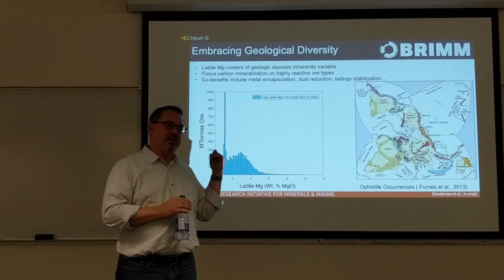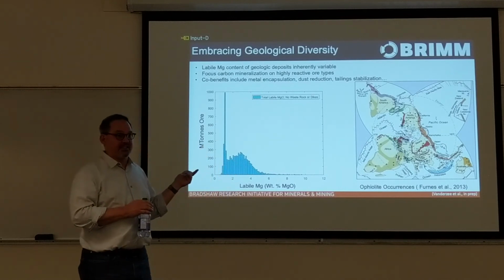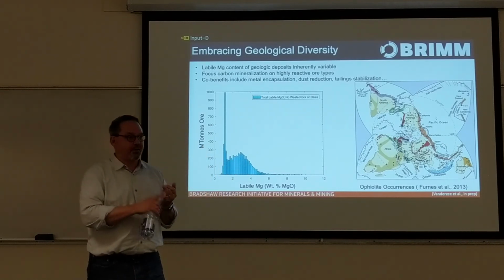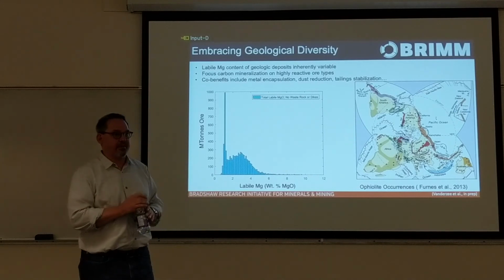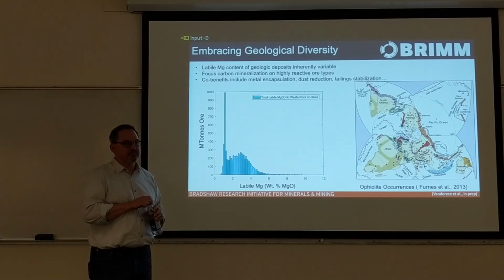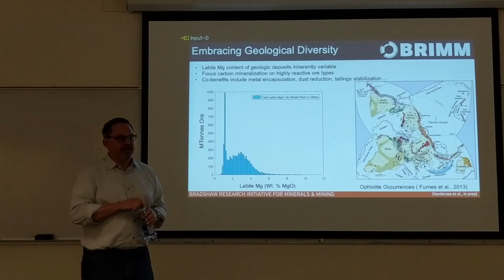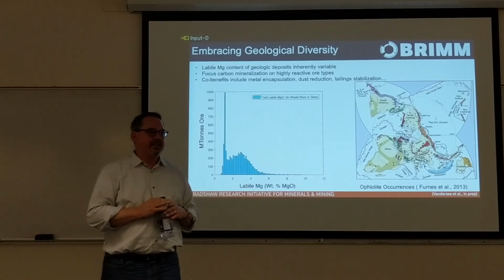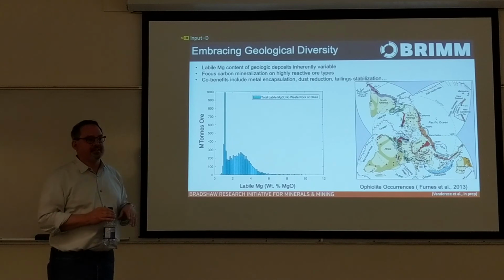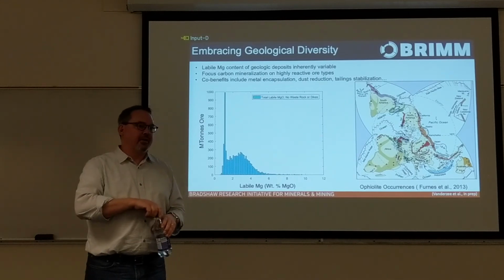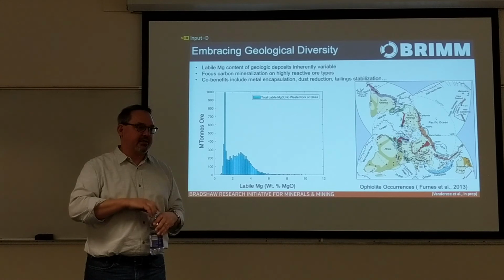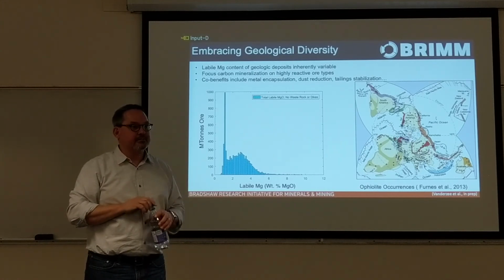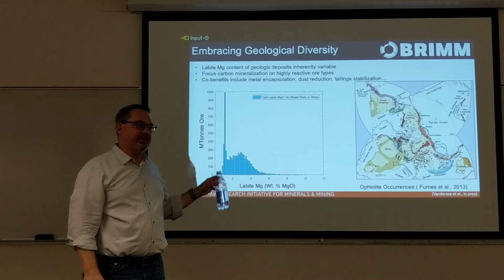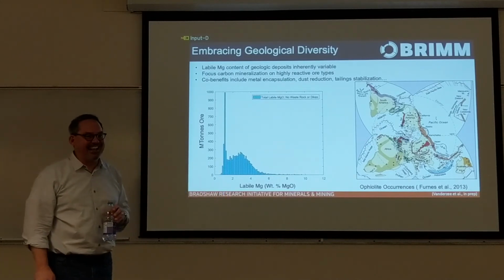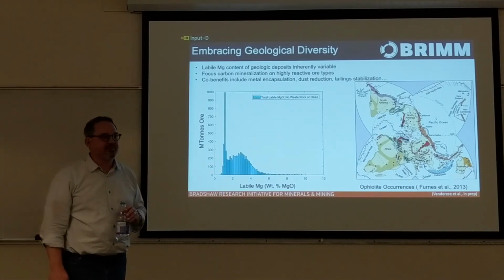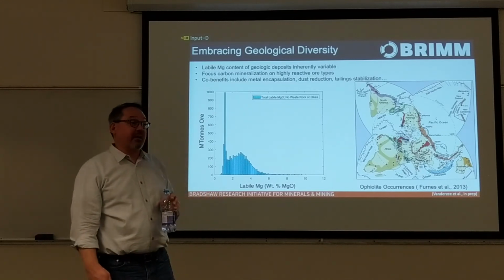The really nice thing about the ultramafics and using CO2 is that your anion is the CO2, so you don't care if it combines with the cation. That's actually what you're after. So I'd say that, because of those reasons, this is the best place to start, and we haven't mapped out the rest. Obviously, if you could get into porphyry space, the magnitude is significantly higher. We haven't made this work yet at 1 million tons per year. Well, 40,000 tons per year isn't bad.